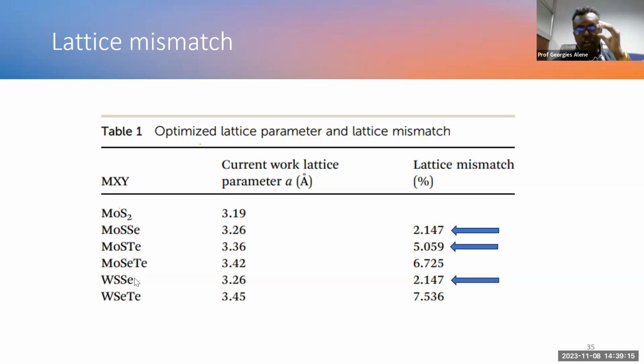So the first step we have done is when we make the heterostructure, we need to calculate the lattice mismatch. The study shows that when you have a lattice mismatch of less than 5%, it is actually possible to realize it experimentally. So what we have done is we have calculated the lattice mismatch, and as you can see, three of them have a lattice mismatch which is 5% or less than 5%. So we selected these. For the others, we exclude them from our study because it is not possible to realize them experimentally according to literature.